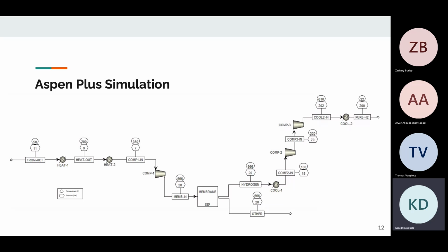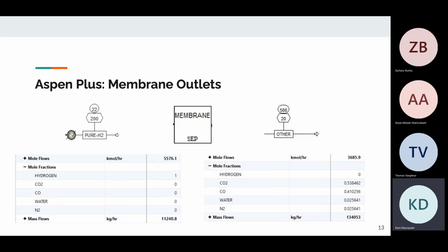This resulted in nearly 100% hydrogen recovery, which is stored at room temperature being 22 degrees Celsius and the appropriate pressure of 200 bar. The hydrogen is now ready to be stored in pipelines. All other waste exiting the membrane has conditions of 566 degrees Celsius and 20 bar. Now let's take a closer look at the outlet results achieved from our simulation.